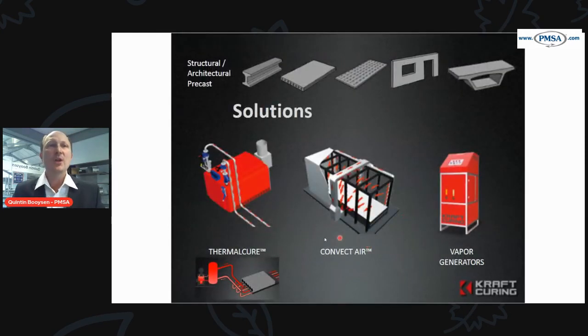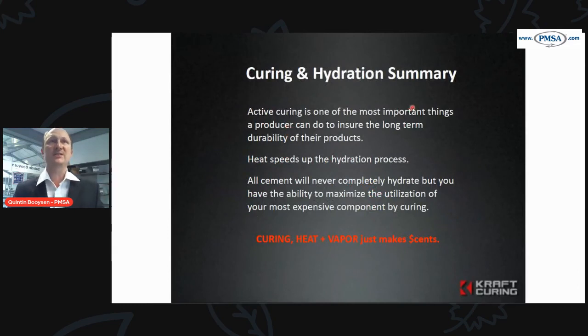Other methods are thermal curing, I'd mentioned earlier, where we can actually introduce heat underneath the systems. So we can put it underneath our concrete. So we generate heat, we pump that hot water through pipes underneath, and we put in an external heat source. But for these sort of structural elements, we can use convected air, we can circulate warm air and moisture, we can use vapor, or we can use indirect, which is the thermal curing. Curing and hydration summary.